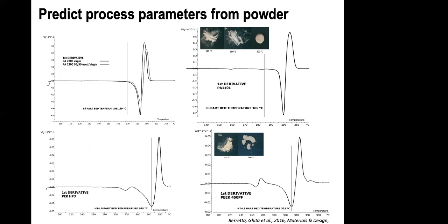So in the picture on the left, you see the PA 2200 virgin, so that is a PA 12, so it's a nylon 12 grade. We included virgin and also 50-50 used and virgin. If we look at the operating temperature, the bed temperature is 169, well outside the melting peak. Also, if we look at PA 11, so this is nylon 11, on the top right, we can see again that we operated at 185, but still outside the melting peak.